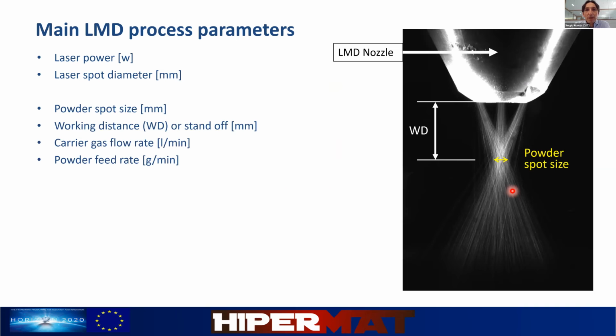Regarding the powder, the main parameters are the powder spot size, which is the minimum diameter at the powder cloud. You can see here, this is the powder spot size. The working distance is the distance from the end of the nozzle to the powder spot size. And it's important to adjust this working distance properly.